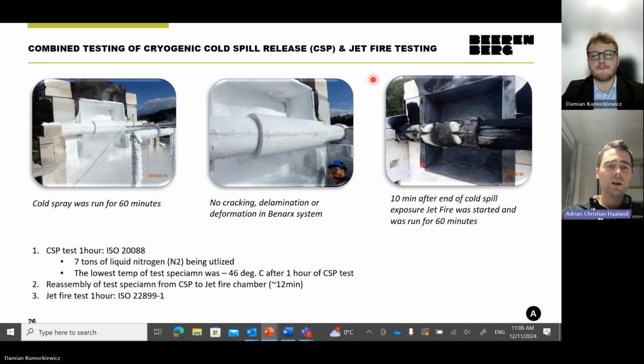And to put the amount of liquid gas used here into perspective, for one test like this, for a jet exposure, we use 7 tons of liquid nitrogen. It's almost the entire truck, which you saw in the picture previously. And you have to evacuate quite a big distance because there's so much nitrogen in the air that it's actually blocking out the oxygen. And everything is like a winter wonderland from the Disney Frozen movie.